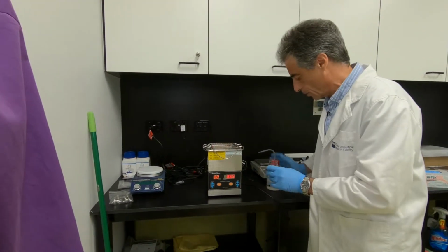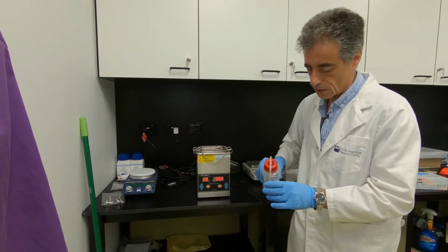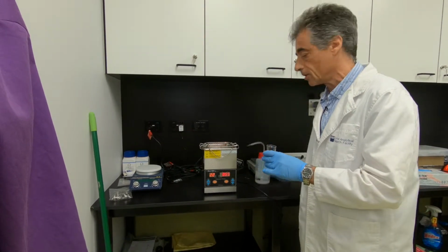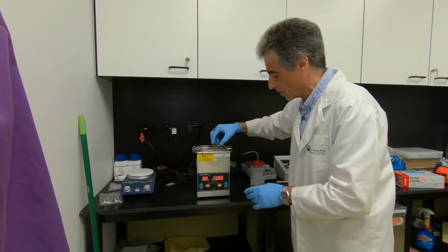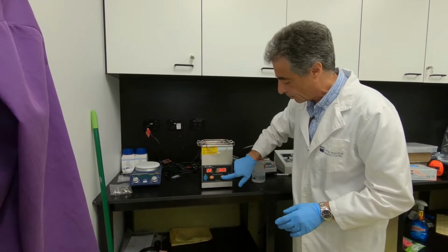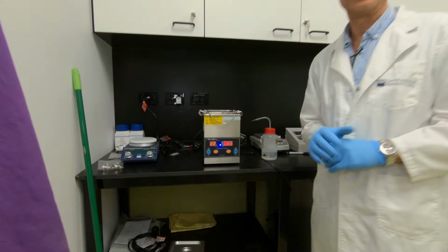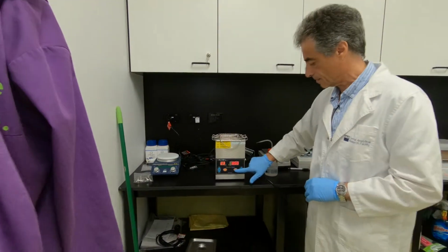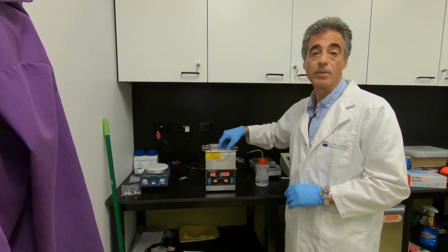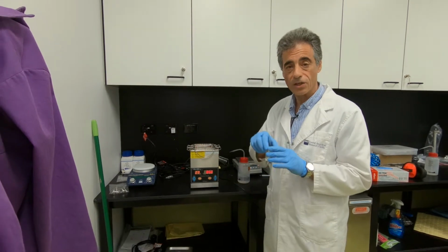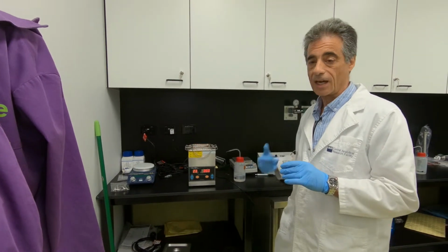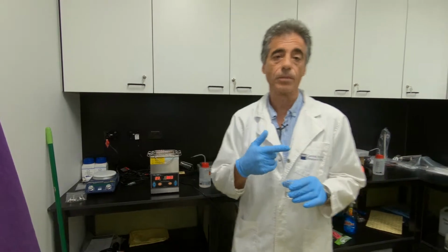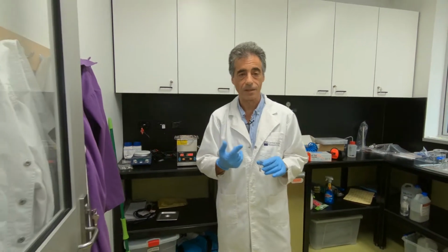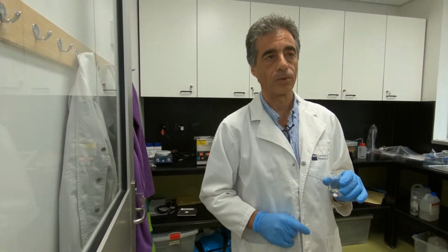So what we do, we fill this beaker with solvent, in this case alcohol, and we can repeat this with acetone and deionized water. And we start the ultrasound. And this goes for a couple of minutes. Once we finish and we do the 3 times cleaning, we go back to the bench and we start preparing the sample onto the sample holder.